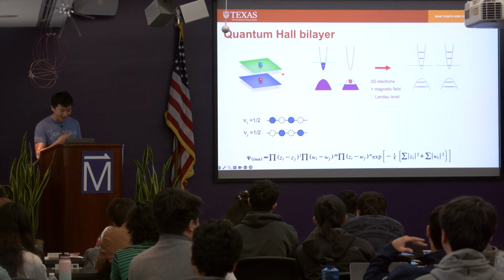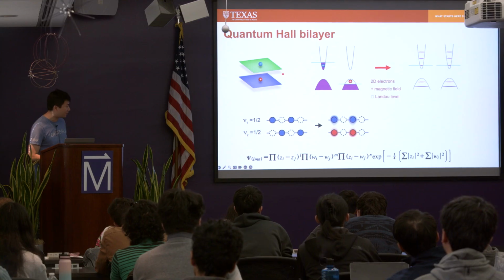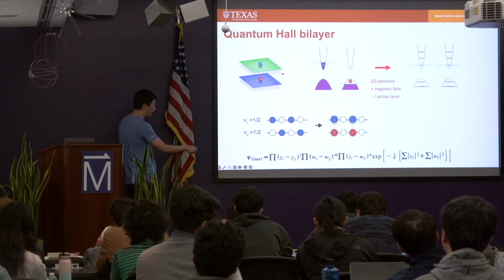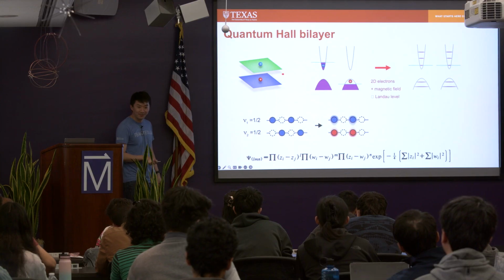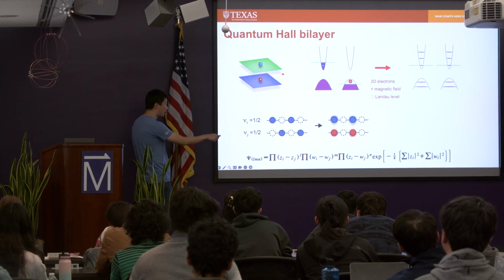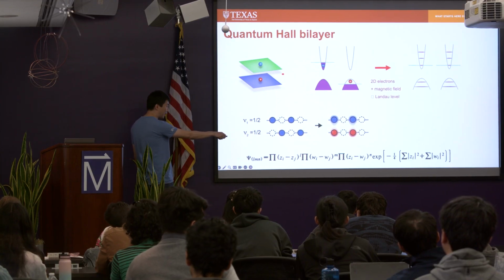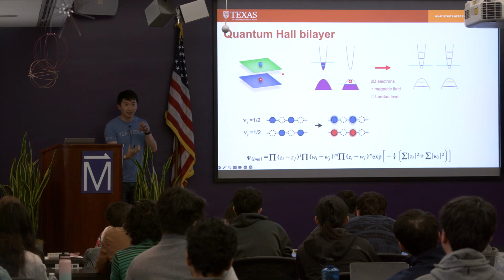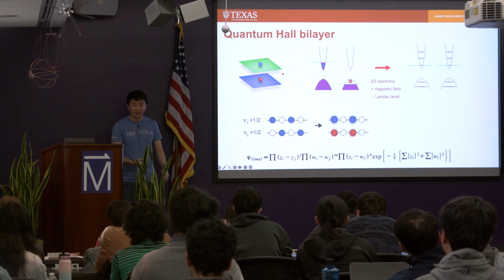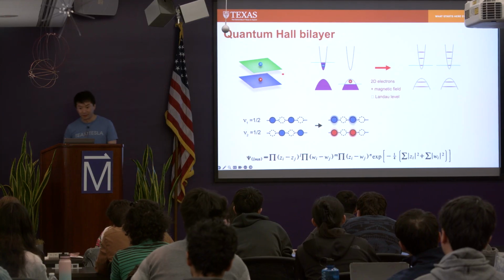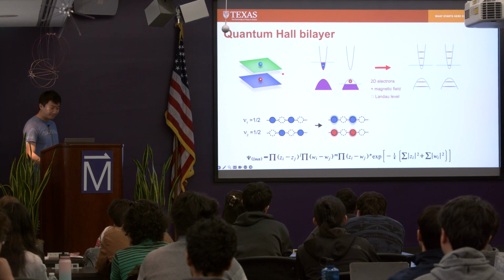To see where this goes, all you need to do is to do a particle-hole transformation on the bottom layer. Instead of looking at electron, we just look at hole, right? So what the state does is that electron on one layer is always aligned with hole on the other layer. It's like there's exciton pairing, right? And at low enough temperature, this will give you a condensate phase.